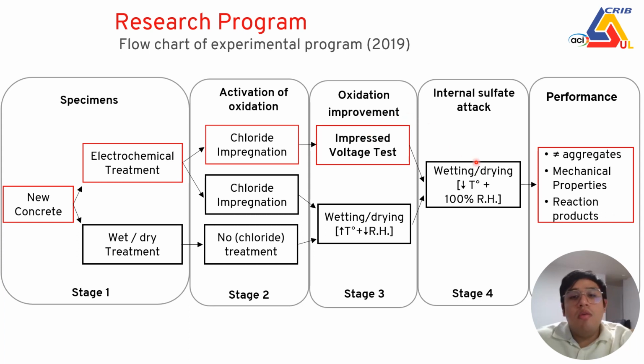And then we try to pass these specimens to a condition to generate the internal sulfate attack with low temperature and high relative humidity to see the performance of the aggregates after being submitted to this treatment.